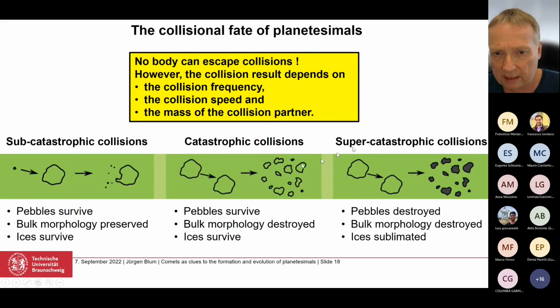And we do distinguish between three types of collisional outcomes. So you saw the catastrophic ones, where the pebbles survive, where the bulk morphology is completely destroyed, but where the ices also survive because the impact energy is not sufficient to heat the bodies. There might also be subcatastrophic collisions, so at smaller speeds, where everything survives. So the pebbles survive, the bulk morphology survives. You maybe make a little crater, a little bit of erosion, but nothing else. The ices also survive.